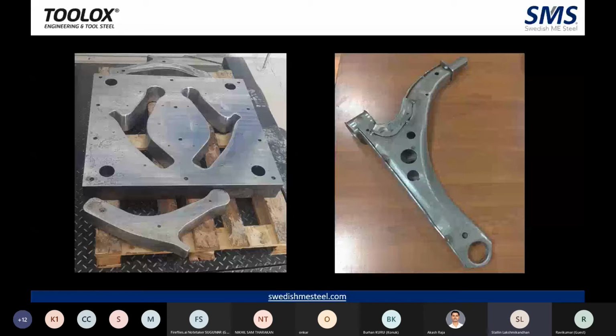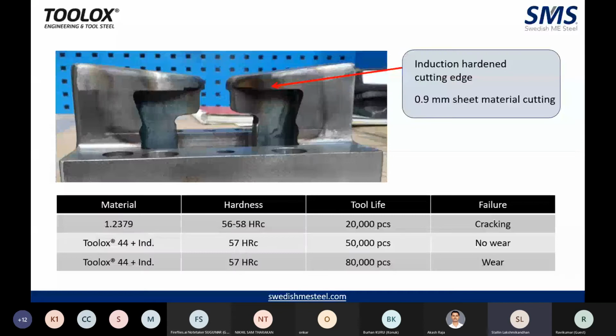So again, for this cutting operation, this is an induction hardened cutting edge. As you can see, the previous metal, D2, failed at 20,000 pieces. The mode of failure was cracking. When you use Toolox 44 plus induction hardening, the tool life you get is 50,000 components, but there is no failure by cracking. At 80,000 pieces you have a problem, but that problem is only wear, not cracking. So anything that has to do with cracking, you can replace the metal with Toolox immediately.